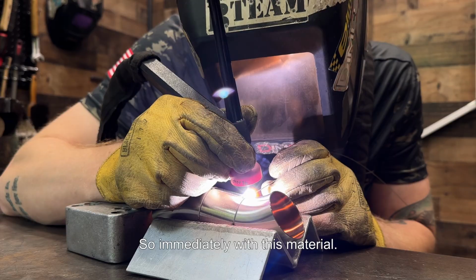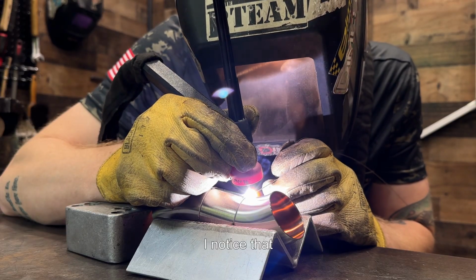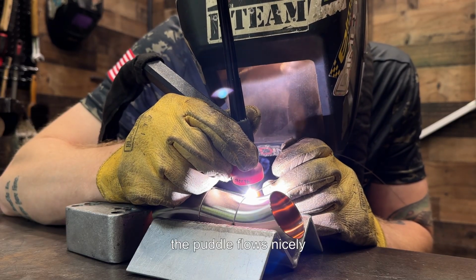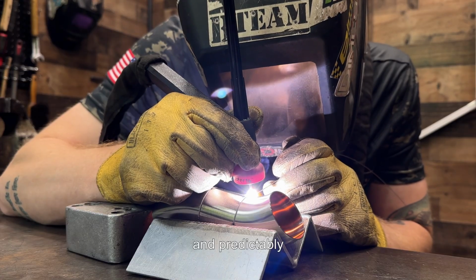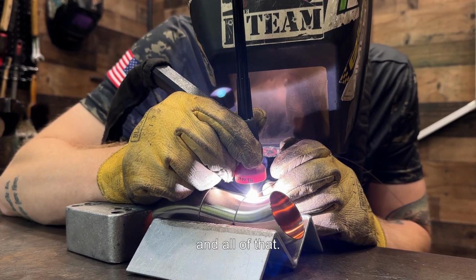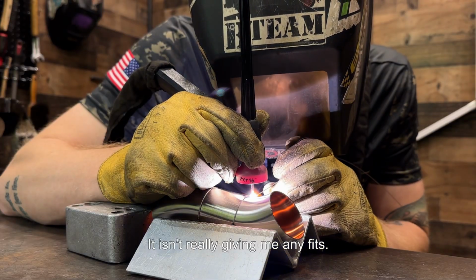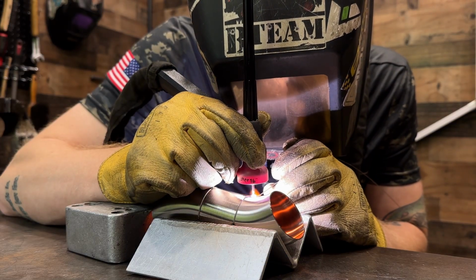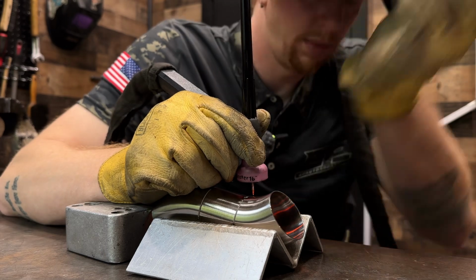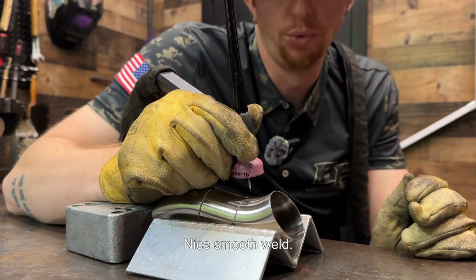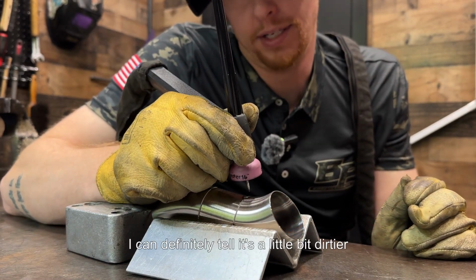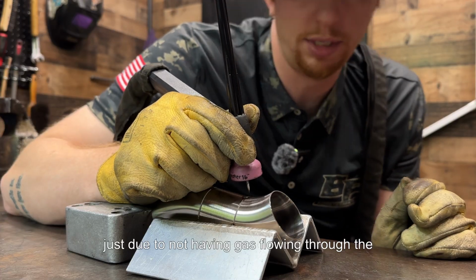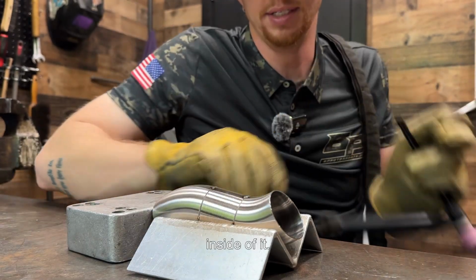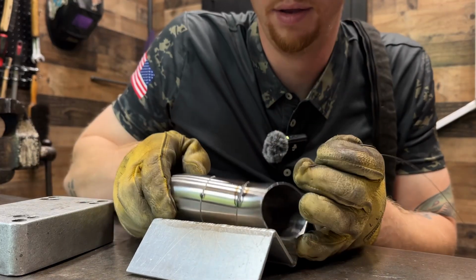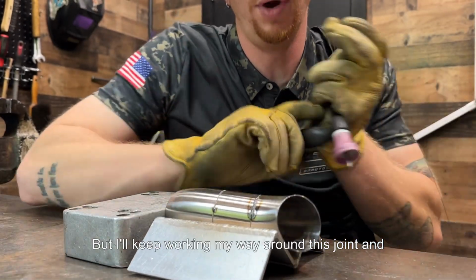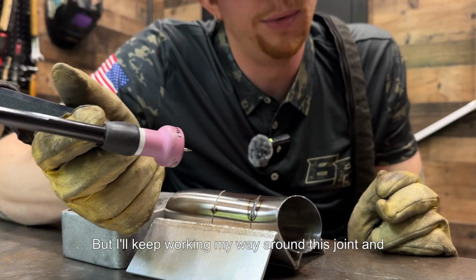So immediately with this material, I noticed that the puddle flows nicely and predictably. It isn't really giving me any fits. Nice smooth weld. I can definitely tell it's a little bit dirtier just due to not having gas flowing through the inside of it. But I'll keep working my way around this joint and we'll see what happens.